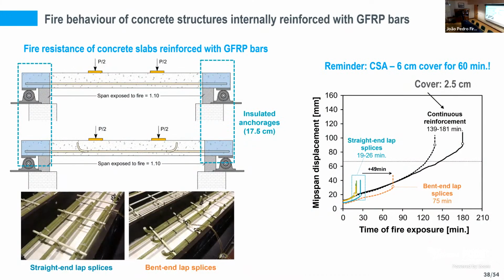In the experimental campaign, as I told you before, we adopted concrete covers of only 25 millimeters, and by adopting this thin concrete cover, but guaranteeing that the anchors of the bars were kept cold during the fire, we were able to attain significant fire resistance, above 2 hours.